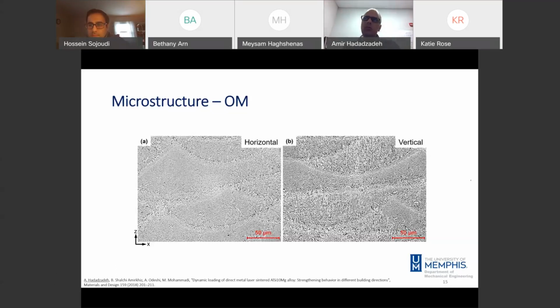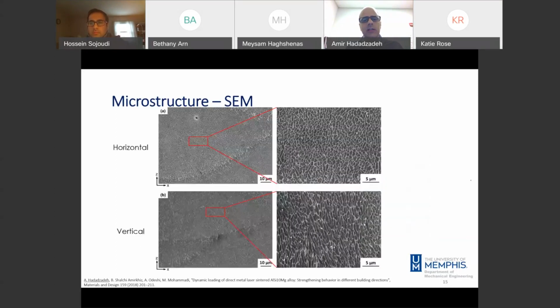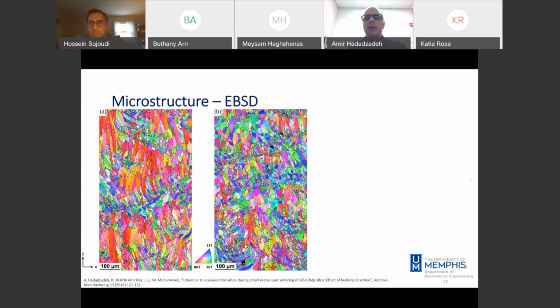Again, another good question. In general, if we go back to literature, there are some fundamental studies on the effect of columnar structure on the properties of AM materials, and this columnar structure usually develops because of epitaxial growth. This is a classic study in the context of welding. And when we have columnar grains, we have a textured material because the grains are developing along a specific direction. Here, for example, we see more red color in the case of the vertical sample. This red color shows that we have a 001 texture. We have a preferred texture here.